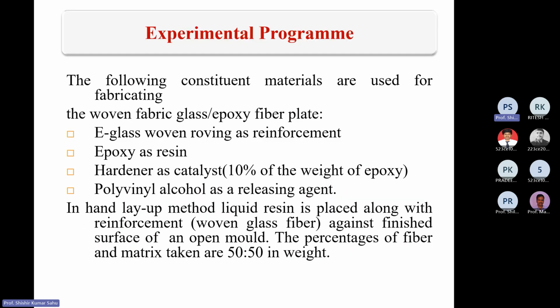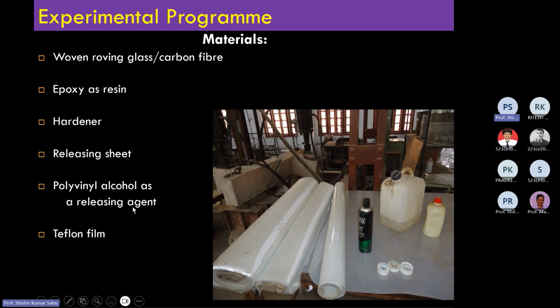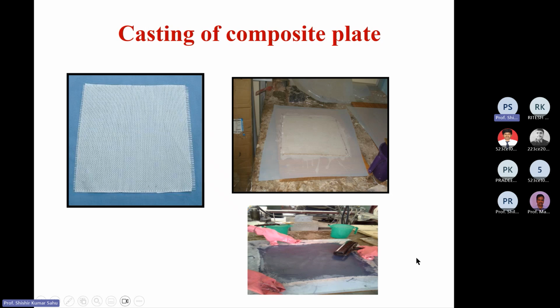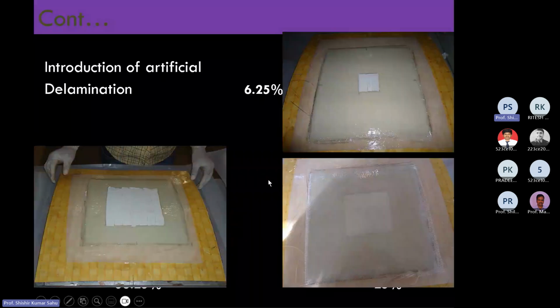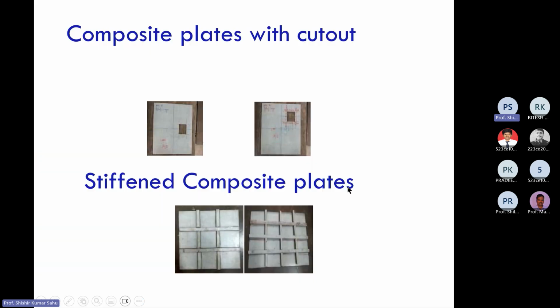Then comes the experimental program. As you can see, glass fiber, carbon fiber, epoxy, hardener, polyvinyl alcohol. So these are the materials being used. This is the fiber. These steps are used to create artificial delamination. So this is the casting of composite plates. This is used for delamination of different sizes. In between layers, we create delamination.